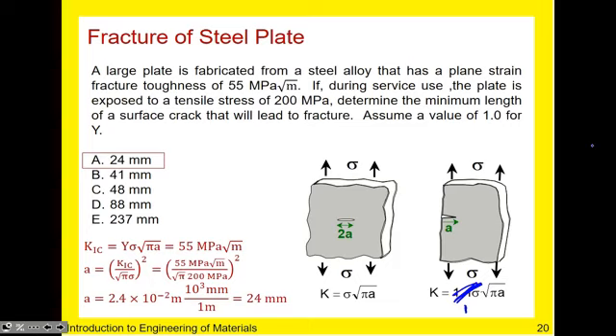And so there you convert the units of meters to millimeters. It's 24 millimeters. So if you switch this equation around, you have your K1C over square root pi, sigma, all of that square root because your A was in the square root before. Plug in your fracture toughness, your applied stress of 200 megapascal, and you get that.